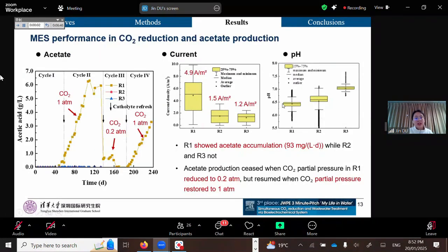Here are the results of this study. For R1, which used gaseous CO2 as the main carbon source, acetate accumulation was observed after 50 days of operation, with an average acid production rate of 93 milligrams per liter per day. In contrast, for R2 and R3, using dissolved bicarbonate as the main inorganic carbon source, no significant acid accumulation was observed even after 140 days.